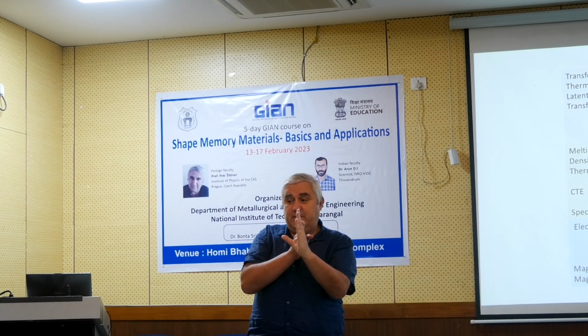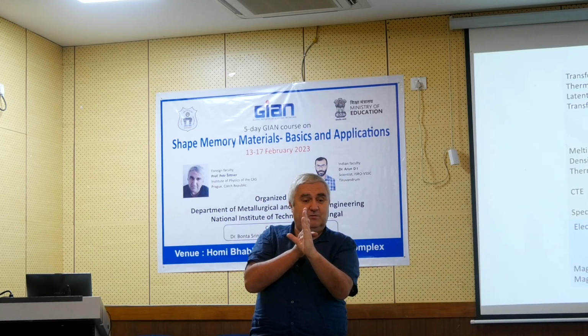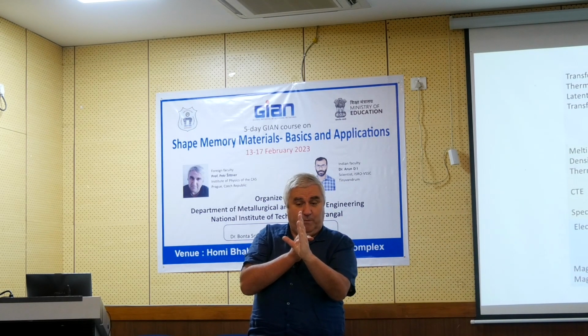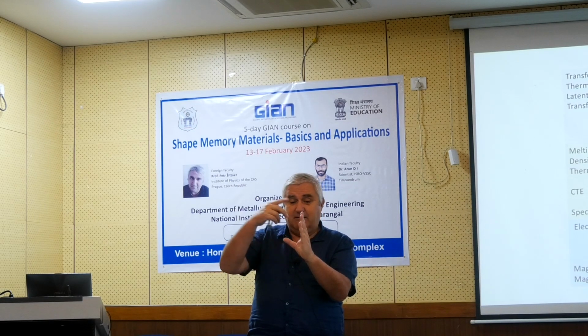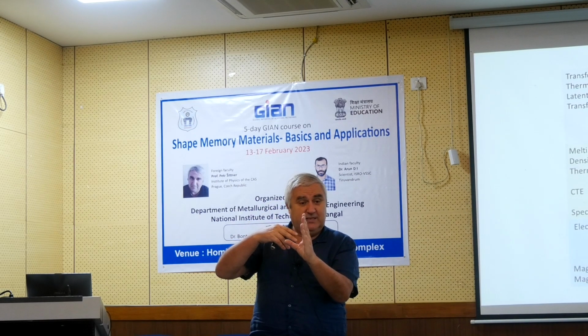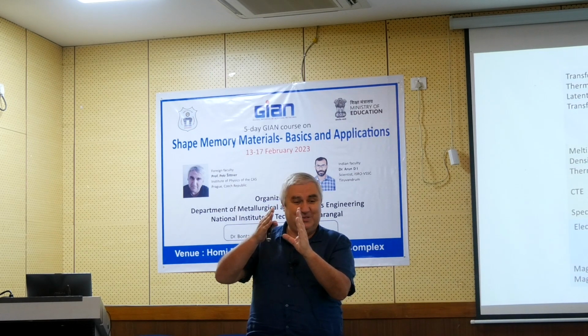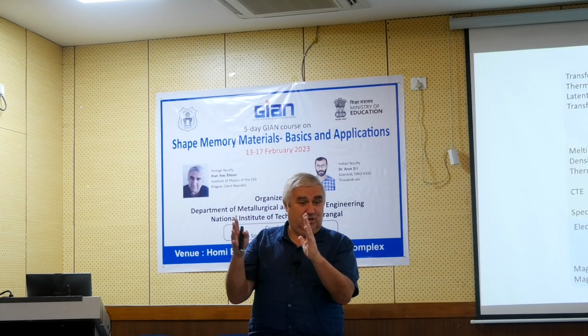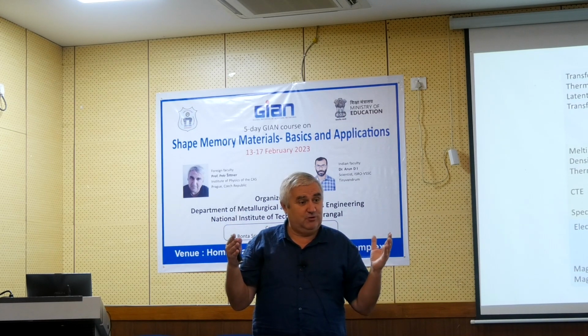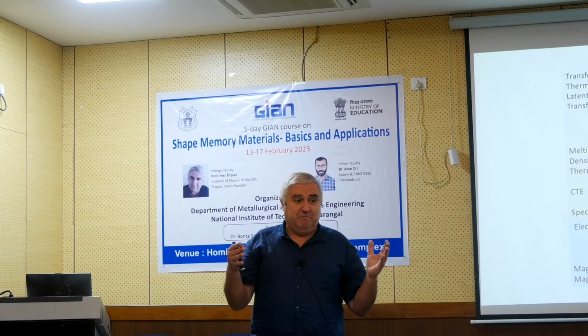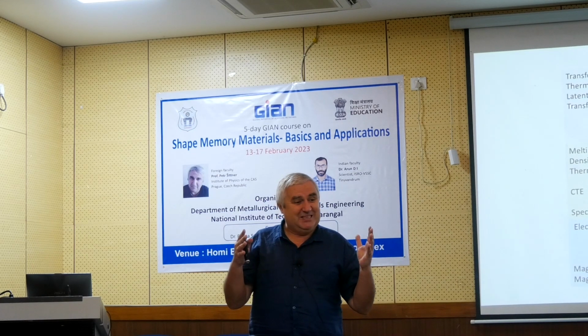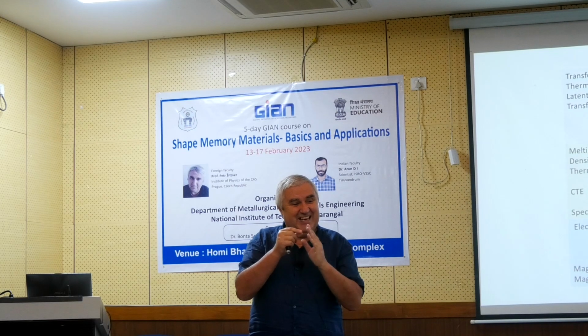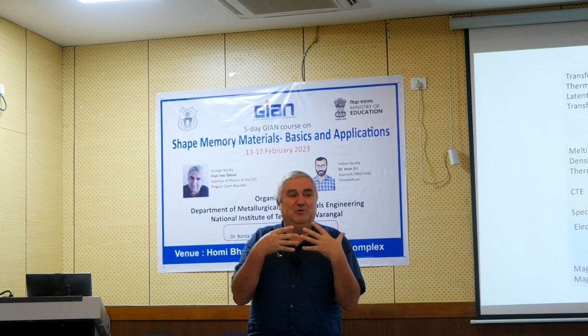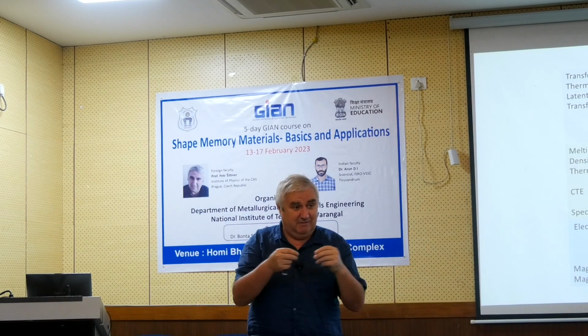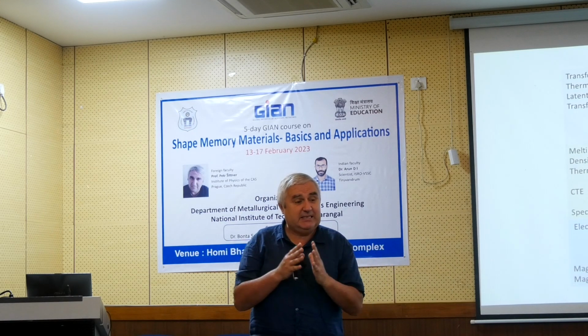There is a famous paper in Science by the German scientist Chluba et al. They show that if you have this nickel titanium copper as a thin film, they can run several millions of superelastic cycles, up to 2 or 3% without any damage. So this would be our dream: superelasticity with millions of cycles. The problem is that it works in their case of thin film with no defects, but if you want to make nickel titanium copper in bulk wire, it doesn't work. But it's still much better than NiTinol.